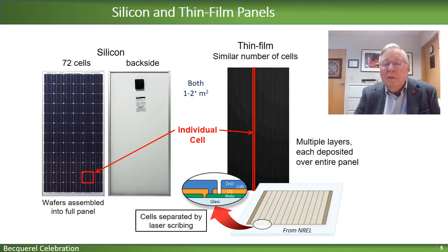So starting with a piece of glass and then a metal, in this case molybdenum, and then that little cut in the green there is done by a laser scribe. And what that allows is that the left side is electrically isolated from the right side. And then we come along with CIS, in this case, for absorber material in orange, and then it's also cut, but that cut is a bit offset.